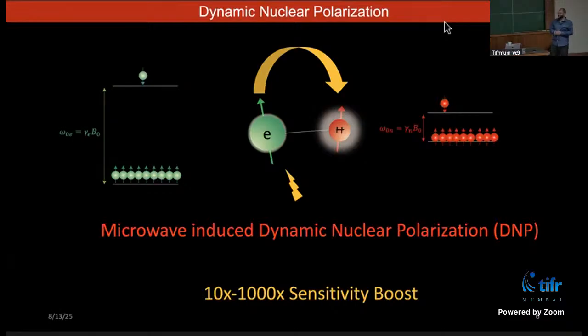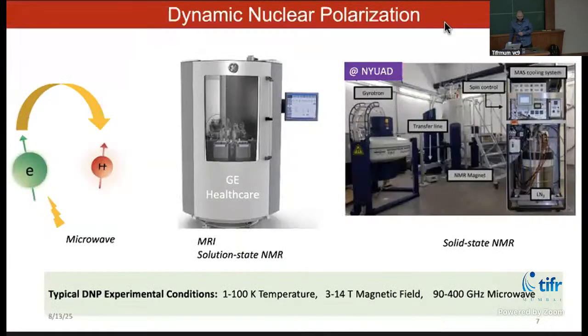This means that if someone can achieve a sensitivity gain of 1000, whatever measurement one would do with a conventional setup, if it takes 1 day or longer, with DNP NMR it can be done in a few seconds. So this is what we want to do. Depending on where you want to apply this technique, whether for MRI, solution state NMR, or solid state NMR, the technique can appear different.